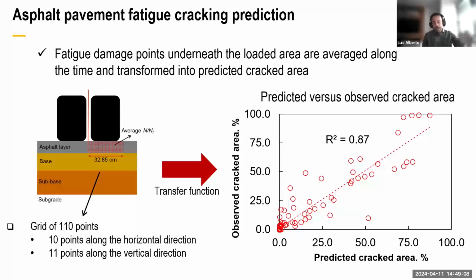But since we are capturing the asphalt mixture RAP dynamic modulus and the relaxation modulus, and we capture all the fatigue properties by using the S-VECD analysis, when you combine the asphalt mixture properties in the FlexPave framework, you have different pavement responses according to the climate, the traffic level, and the pavement structure. When you couple these responses to the S-VECD model for those mixtures, the prediction looks to be fine, because we have been applying some RAP mixtures in Brazil using the same calibration, and the RAP mixtures are following the same pattern as the other ones. So it looks like the mechanistic approach is able to capture that, at least so far in our observations.